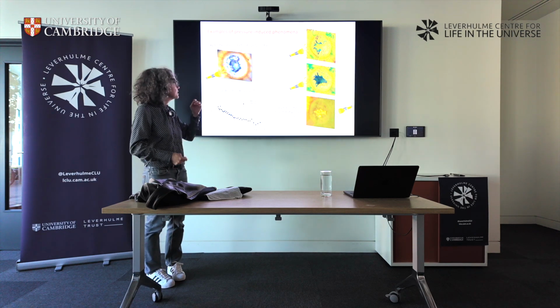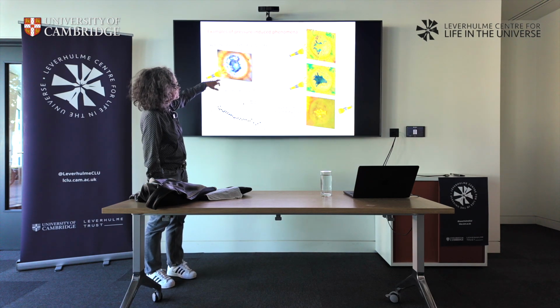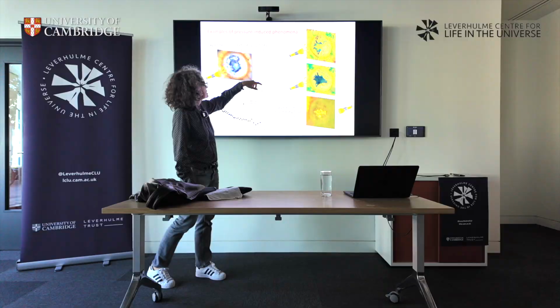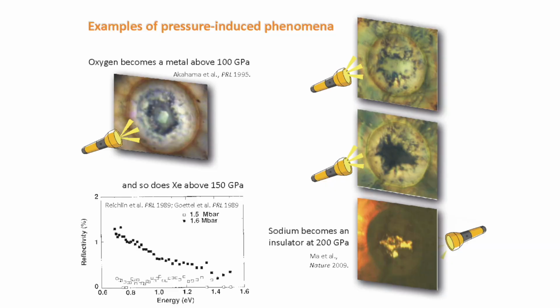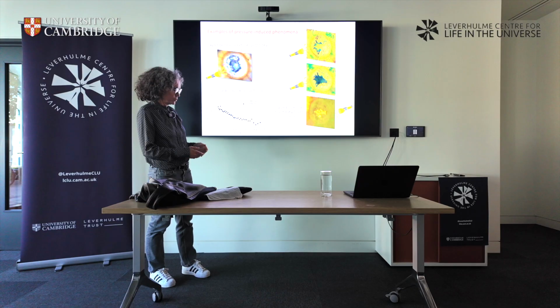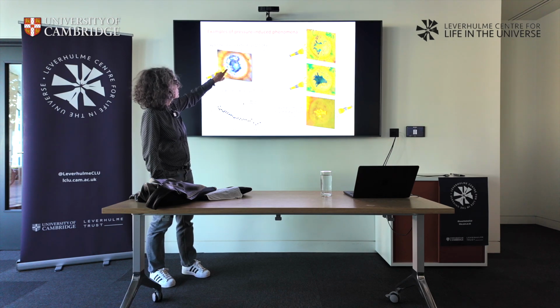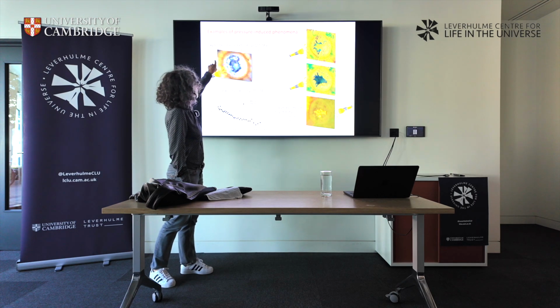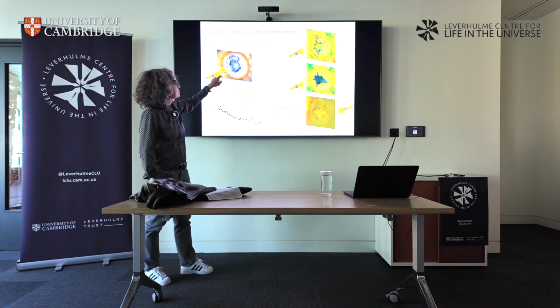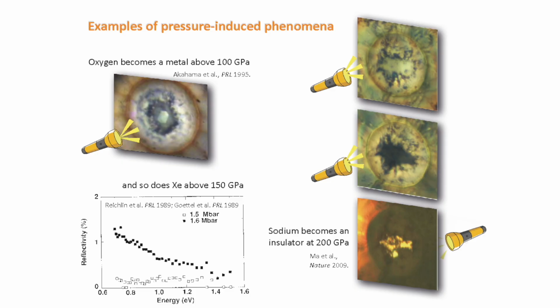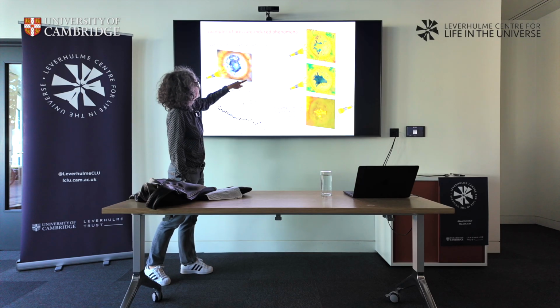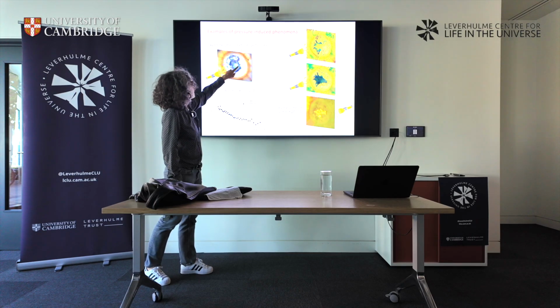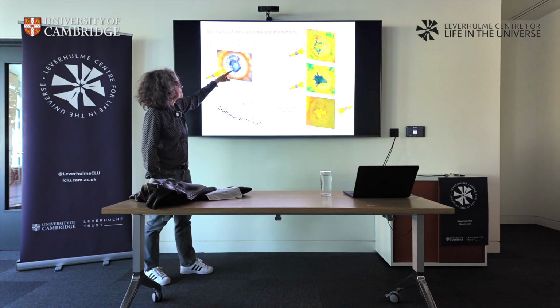So that's one of the, so all of this, it's a little bit blurred, sorry. All of these images are photographs of a diamond anvil cell, which you look at through a binocular with the light from the top. This is a gasket, usually made of metal, typically rhenium. The imprint, the indent you see, is the diamond tip with the diamond faces. That's the diamond culet. There is a hole in it, and this shiny hexagon here is a crystal of oxygen.